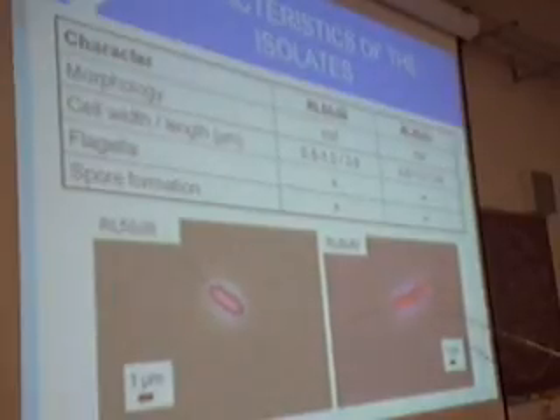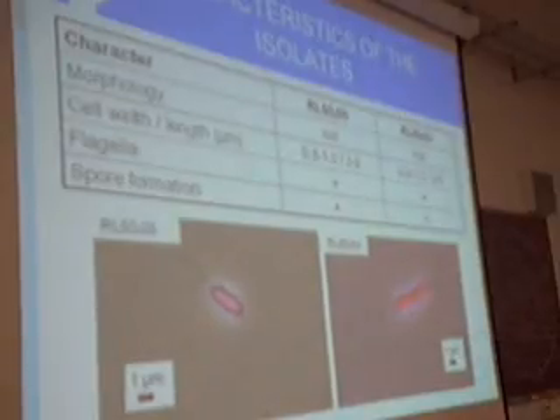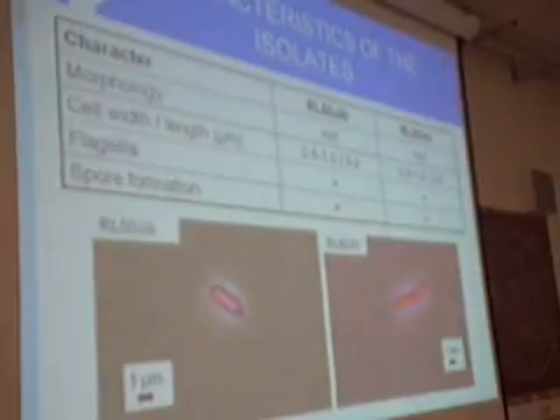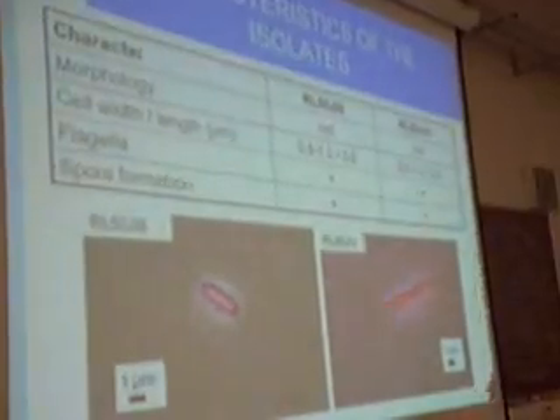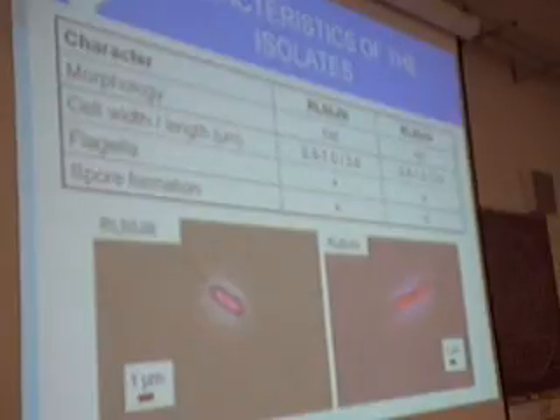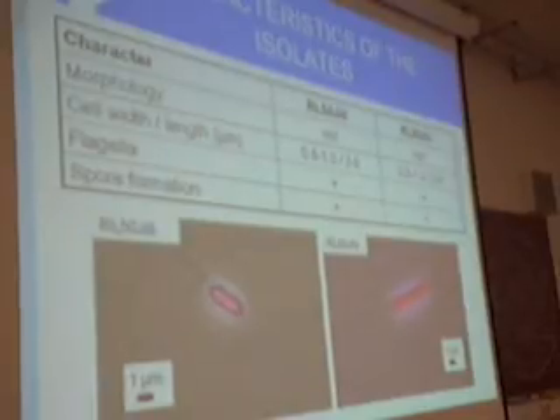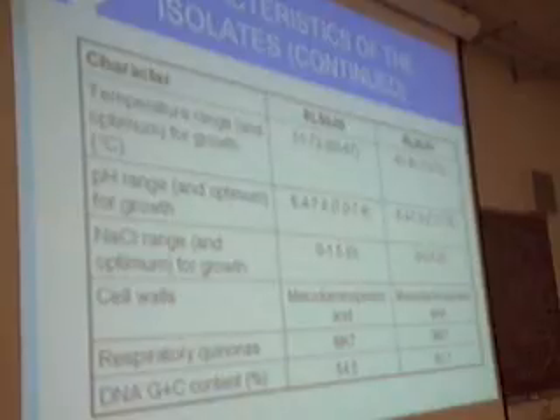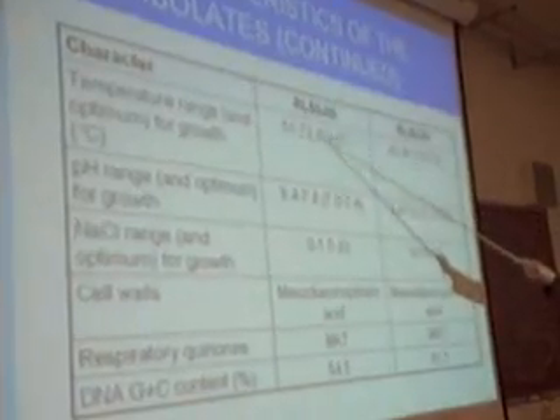And here are pictures of them, and they were both rod-shaped bacteria. They were motile, so they had flagella at both ends of the cell, and they formed spores which help them to survive in harsh conditions. For example, if the temperature rises too high or if there are not enough substrates for the moment to use. The temperature optima for the bacteria were around 60 or 65 for this one, and around 70 for the other one, but it could go up to 80 degrees.